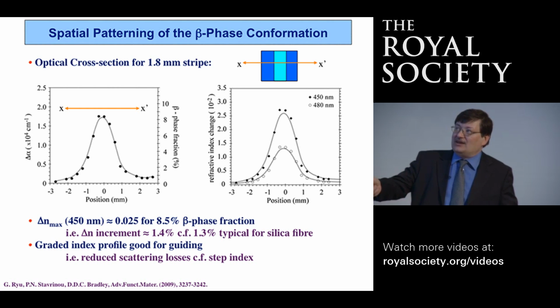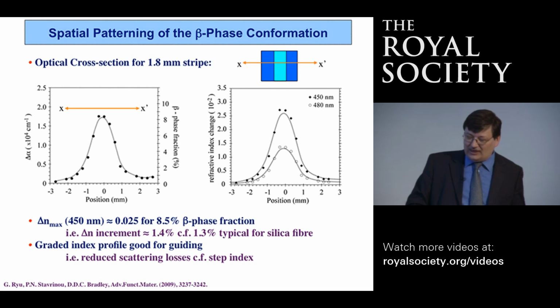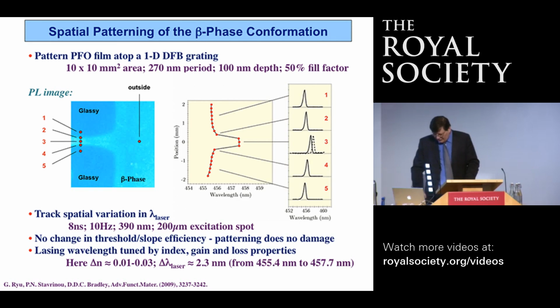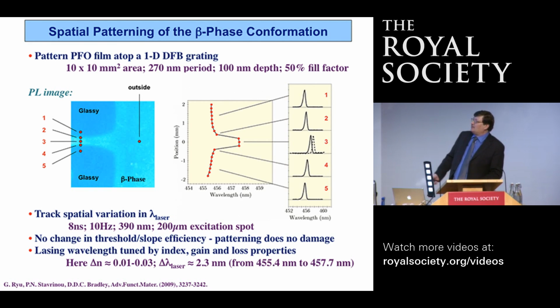We have a nice graded profile here, which is quite good if we're thinking about making guiding devices. We've also looked at making some active structures. You can quite clearly see the beta phase with this turquoise emission, the more typical glassy phase with the deeper blue emission.